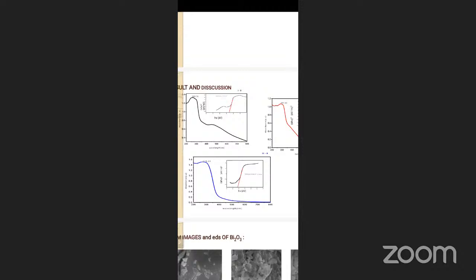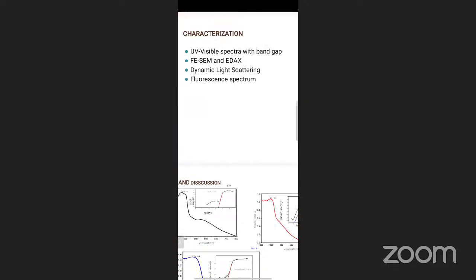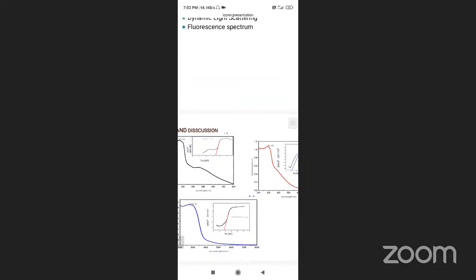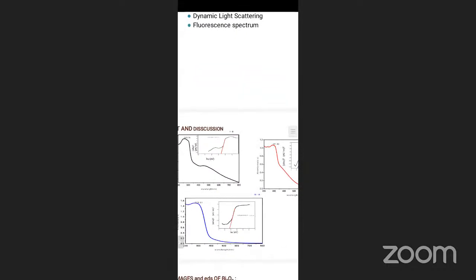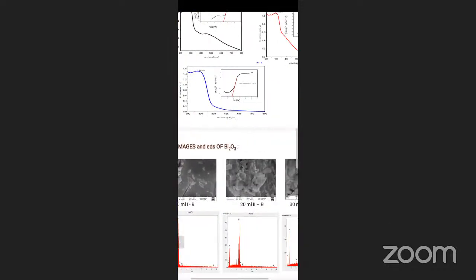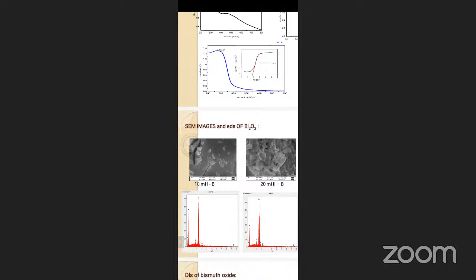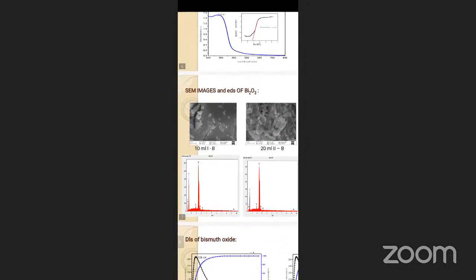In this, the first sample has a high band gap because the particle size is smaller. The particle size increases when the temperature is high, and when the particle size increases, the band gap decreases. Then SEM images of bismuth oxide and the EDAX images.